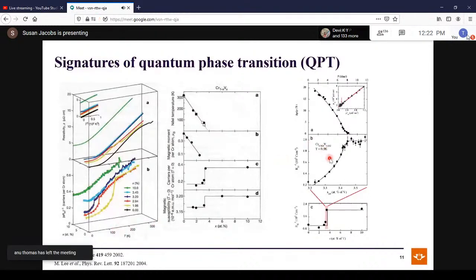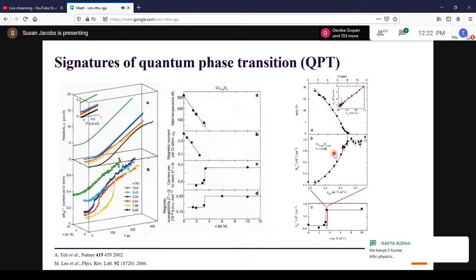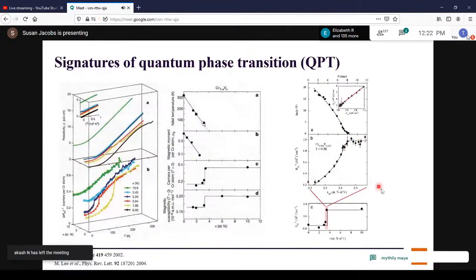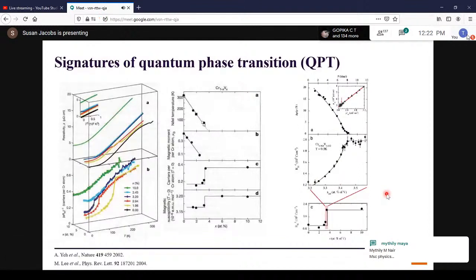On the right, we have again a chromium vanadium single crystal. Now the vanadium concentration is kept constant at about 3.2 atomic percent vanadium, and here pressure was used as a tuning parameter. Here we can see how the normalized resistivity varies, as well as the inverse Hall or the charge carriers, again a sudden drop upon entering the ordered state. So these are some of the signatures we can look out for to see if our system undergoes a quantum phase transition.